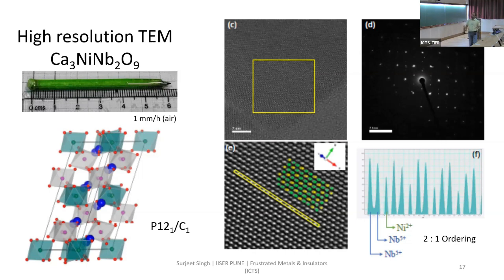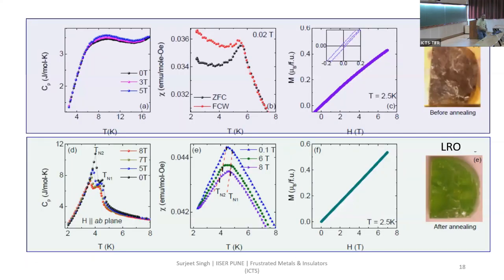So it's completely monoclinic and it has this ordered structure. So once you have them, you would like to study them. And this is what you see. Again, this is the preliminary study. So from the black crystal where you have nickel and niobium randomly occupying the B site, you would expect a glassy ground state, which is what you see over here.